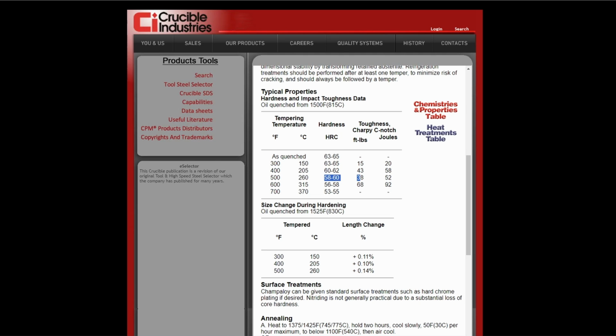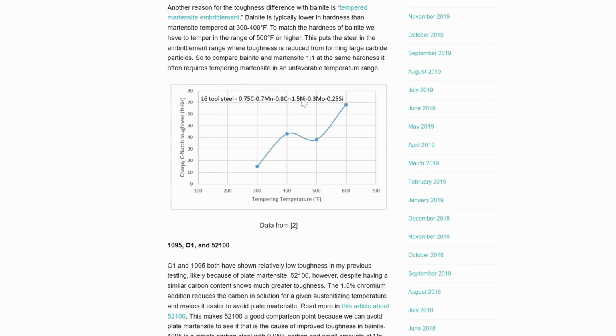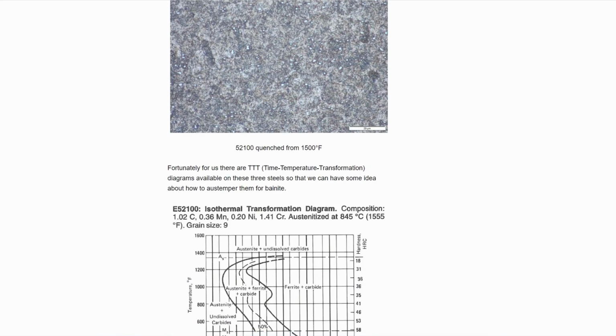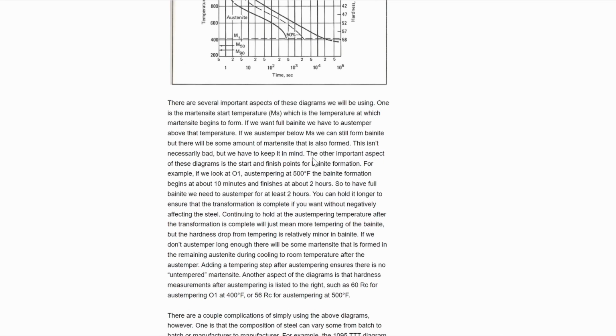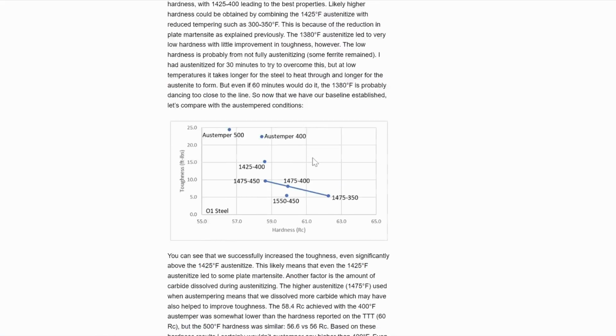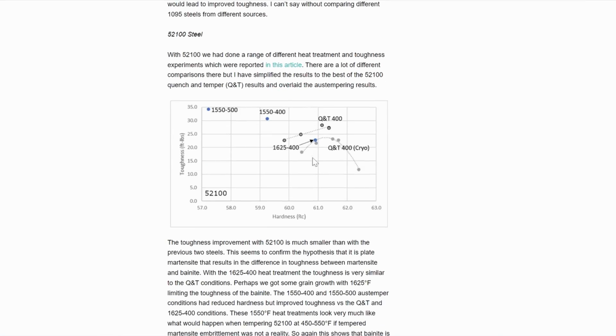But what if you want something in the 59 Rockwell range with improved toughness? Well, a good way of doing that is to use an Austemper. We would hold the steel at some intermediate temperature above martensite and get in that 58, 59 Rockwell range. To have one more example, I did the same thing with 52100. I got quite high toughness in the range of 57 to 59 Rockwell by tempering from 400 to 500 degrees Fahrenheit.